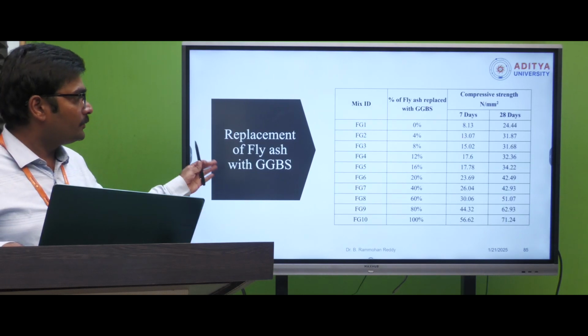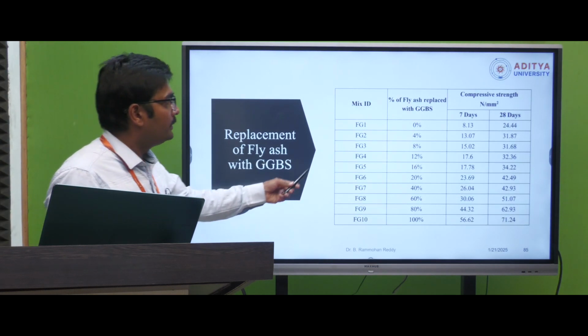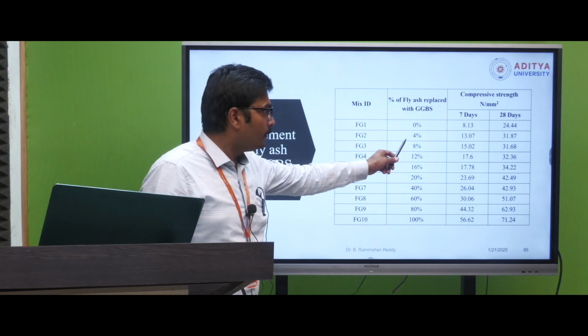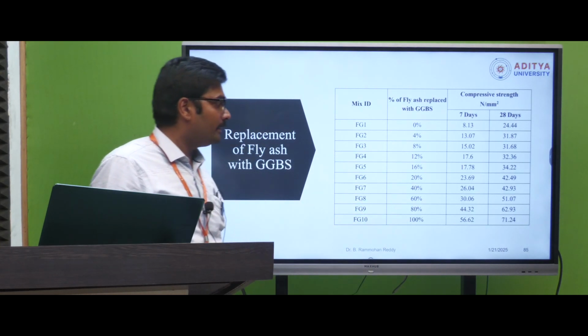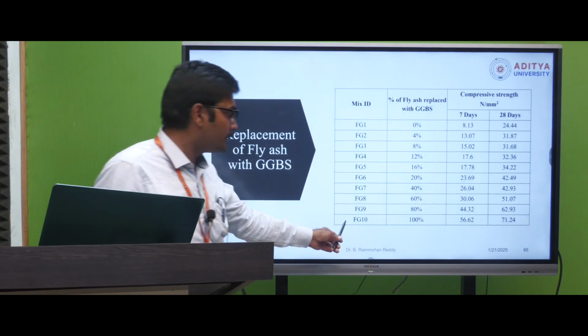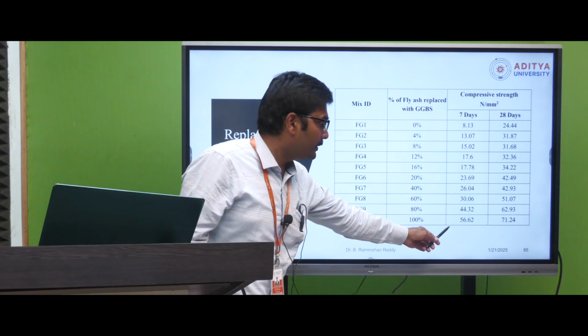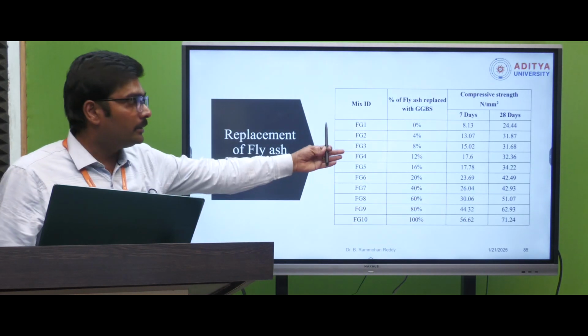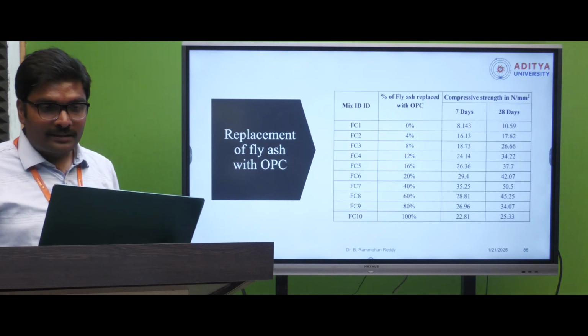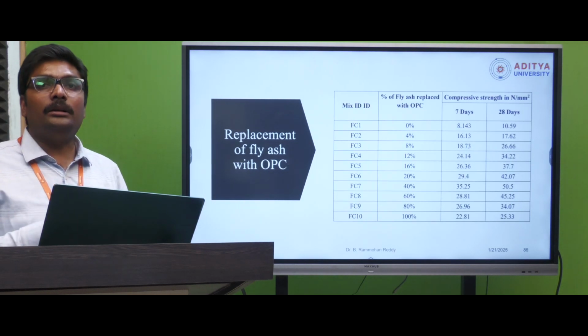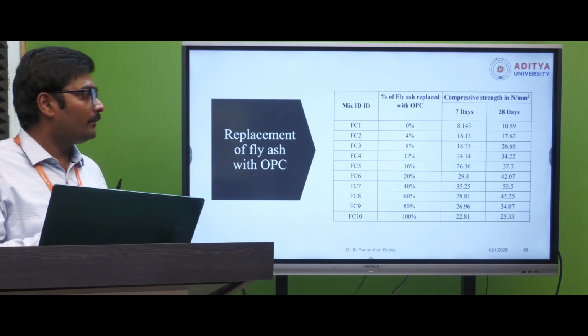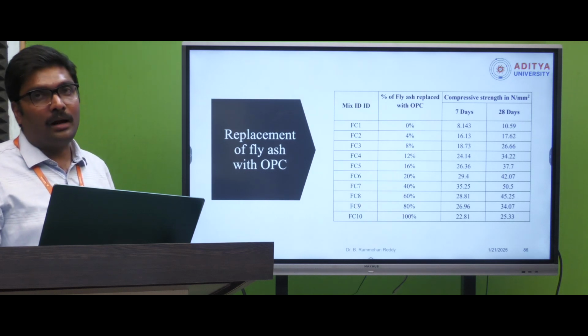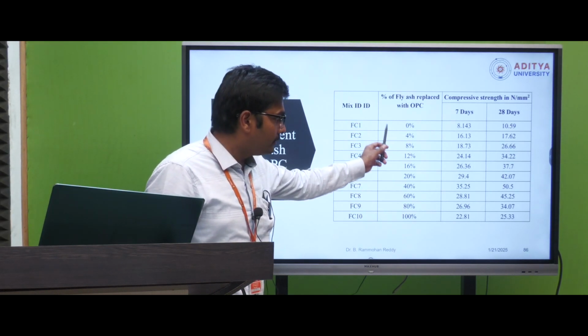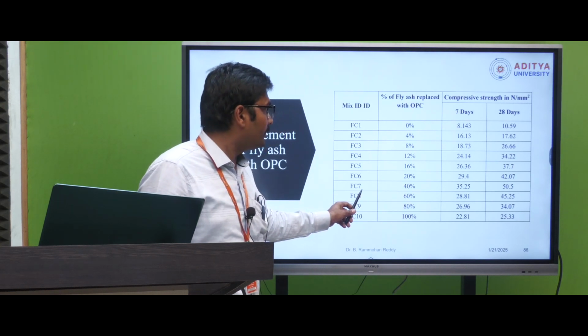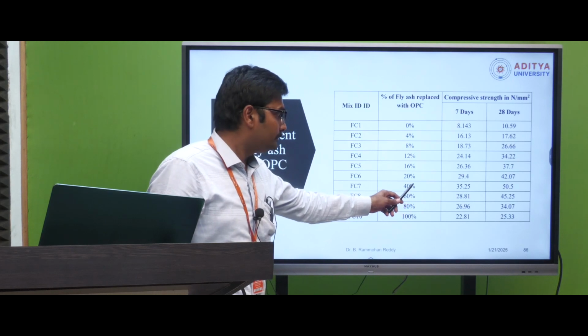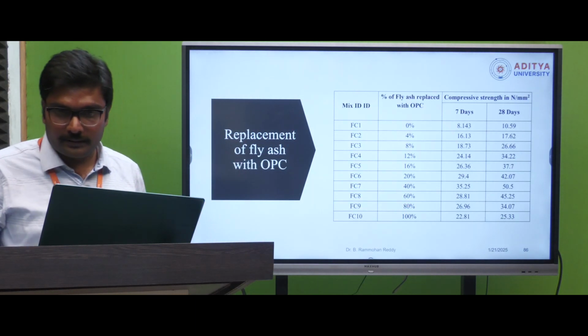And for replacement of fly ash with GGBS, you can see this table indicates the fly ash is replaced with GGBS at 0%, 4%, 8%, and so on, increased up to 100%. And he concluded, you can see these values, that 100% fly ash based gave better compressive strength for 7 days as well as 28 days compared to other mix proportions. Similarly with OPC, he also tried. Generally, geopolymer concrete is used to avoid OPC, but one of the authors attempted to replace fly ash with ordinary Portland cement, and according to these results he says the 40% FC7 mix gave better compressive strength at 40% replacement of fly ash with OPC.